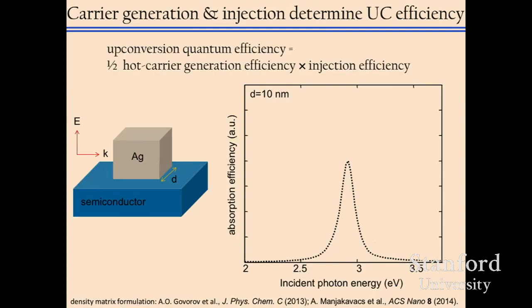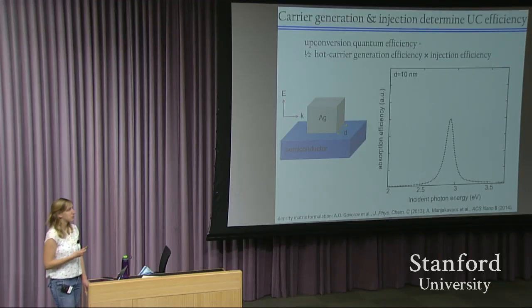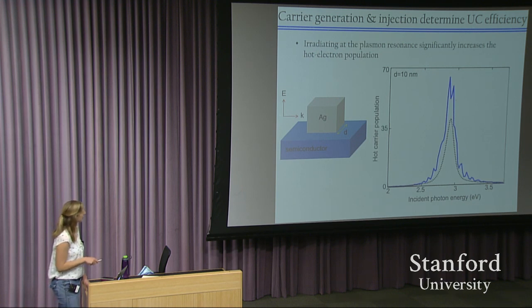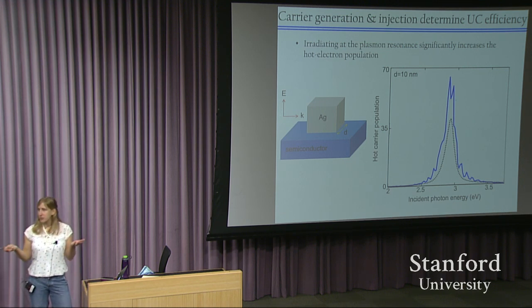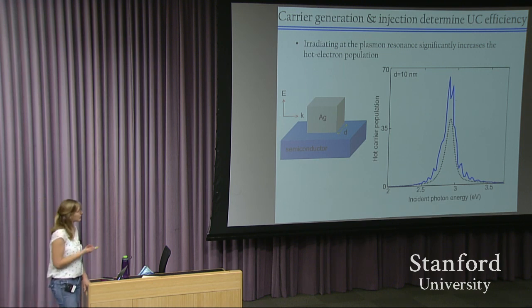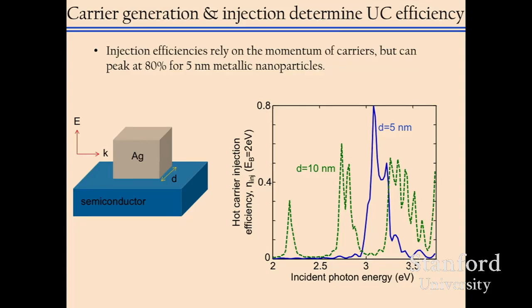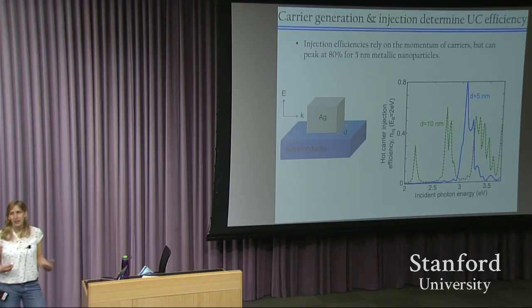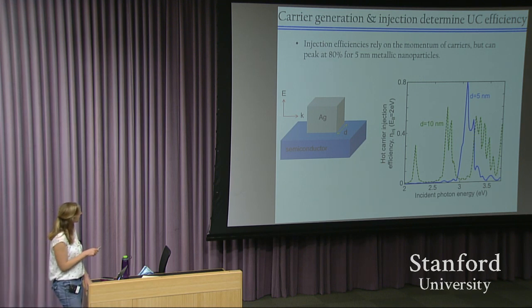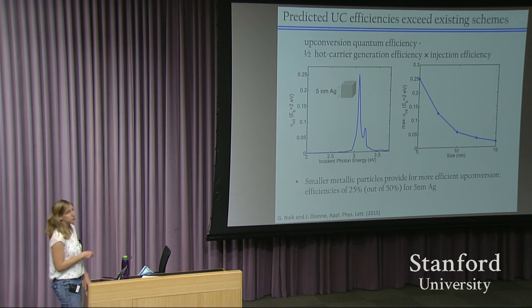And what we need to know, first of all, is how efficiently this nanoparticle is able to generate hot carriers, and then how efficiently it can take those hot carriers and inject them into the quantum well. So the hot carrier population, if you illuminate this nanostructure, tends to peak right on the plasmon resonance. So we get a large population of electrons and holes that can be ejected over the Schottky barrier. And then also, if we calculate the hot carrier injection efficiency, that follows the electronic local density of states. But depending upon the size of the nanoparticle, it can also be quite high, on the order of 80%. So the upconversion efficiency is basically the product of how efficiently we can generate hot carriers and how efficiently we can inject carriers.